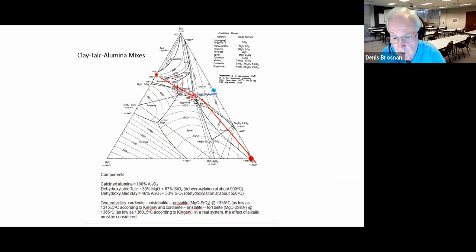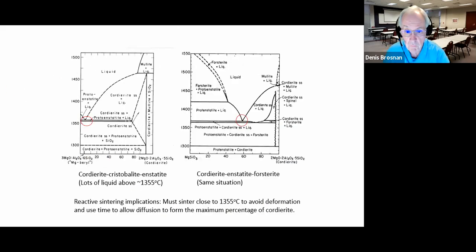And you're going to find out that you have to add a little bit of alumina to hit that composition. You can't quite make the required alumina content with talc and metakaolin alone. You're going to have to sweeten it up with a little bit of alumina to hit that composition.